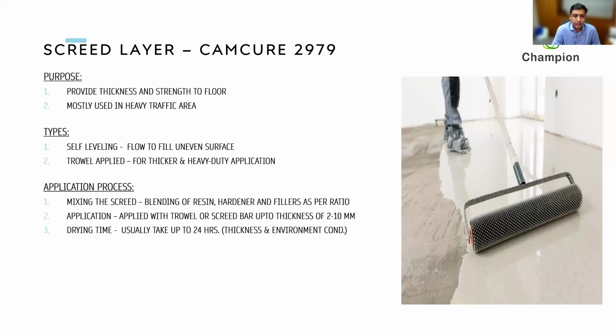The application of the screed can be either self-level or through a trowel, and the thickness can be from 2 mm all the way up to 10 mm. And the thickness depends really on the amount of traffic that the floor would have. The drying time of a screed should be less than 24 hours, but typically most people would want an overnight cure.